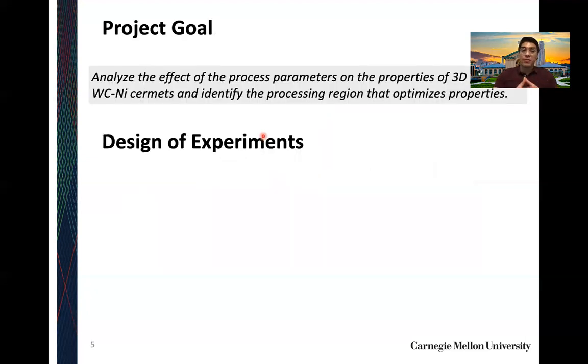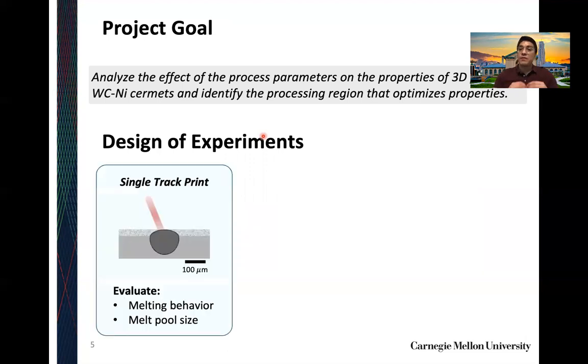And because of that, our project goal is to analyze the effects of the process parameters, the laser power and the laser velocity, on the 3D printed parts of tungsten carbide nickel cermets and identify the processing region that optimizes these properties. And to do that, we pretty much took on a series of experiments. The first being a simple single track experiment where we essentially evaluate the melting behavior of our composite powder as well as the melt pool or melt track size.